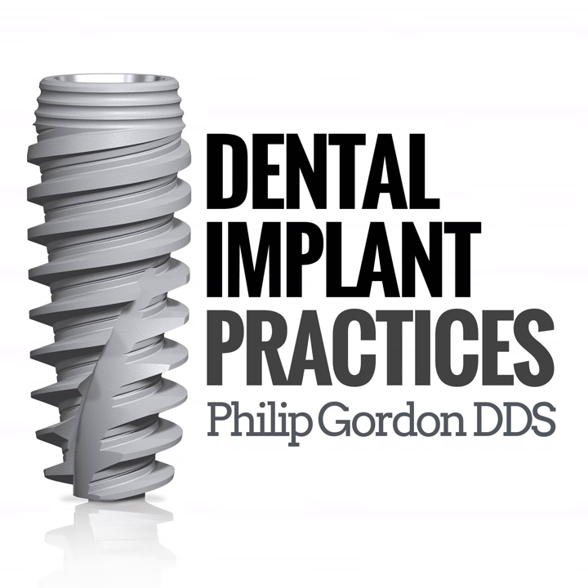You were there during some pretty awesome times. The Steri-Oss system developed by Jack Hahn rolled into the Replace, which was the workhorse of dental implants for over a decade worldwide. What was it like to be in those beginning eras with Nobel BioCare and then the transition to Glidewell? When we came out with Nobel Replace, especially with the internal connection, it was always a good seller but the internal connection was another level — we couldn't make them fast enough. We came out with TiUnite after that, which had manufacturing challenges because we were working with commercially pure titanium instead of alloy titanium, which requires more finesse to make a stronger implant. But it was a heyday of implants. In the mid-2000s we were just making implants and delivering them as fast as we could because the demand was just insatiable.